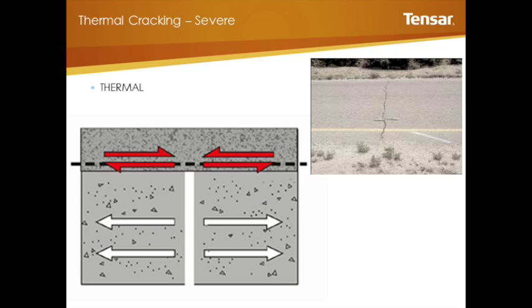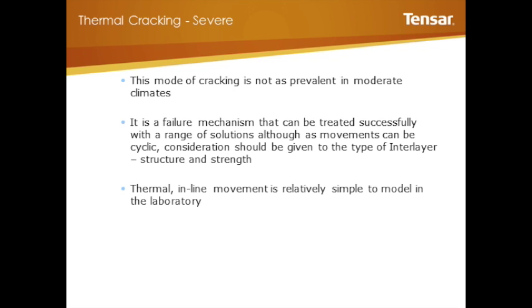The last severe one is thermal cracking. And why is thermal cracking so severe? Because with respect to our product, we put it in, and it's parallel to the relative movement that's taking place. So that is why the structure of the product now plays a key role in how you can transfer stress onto the reinforcing element. So paving grid, which was mentioned right in the beginning, is better suited to this type of application because your movement has to transfer the stress parallel to the reinforcing product. So an open structure product is very well suited to this type of application.